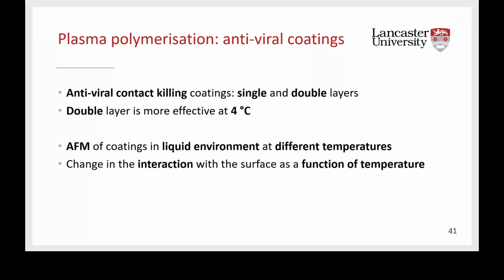So just to briefly sum up, in our research group, we prepare some antiviral contact killing coatings in a single layer and double layer configuration. And they're all effective against COVID-19, but the double layer is more effective at 4 degrees Celsius, and we're trying to understand why. We use some AFM measurement in liquid at different temperature to sense the interaction with the surface, and we could actually see a change in interaction as a function of temperature, but we couldn't spot for now any difference between the single layer and double layer configuration. But this is ongoing research, so hopefully we can find something.